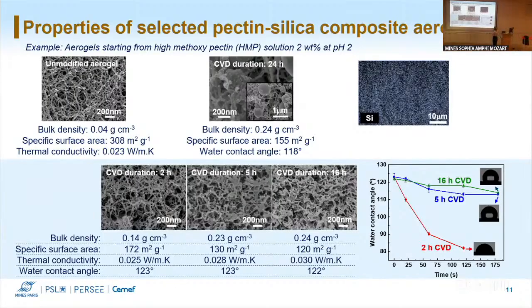Okay, so only for the contact angles, right? The variation. Yes. So for the contact angle measurements, usually I measure 1 or 2 materials and at least 2 or 3 droplets on the surface. And I get the variation. Usually I get very consistent results. So the variations are very small. Very small, okay. Yes, for the contact angles. And for the other ones, how do you evaluate the uncertainties? For example, for thermal conductivity?